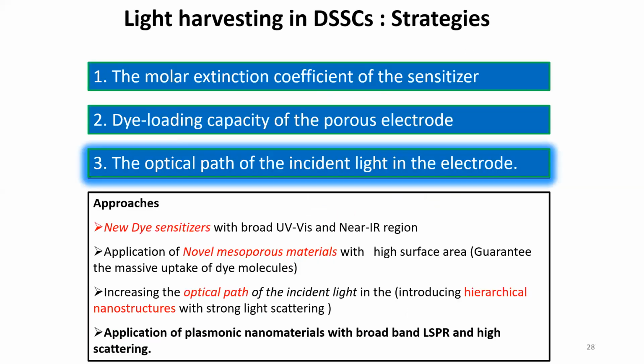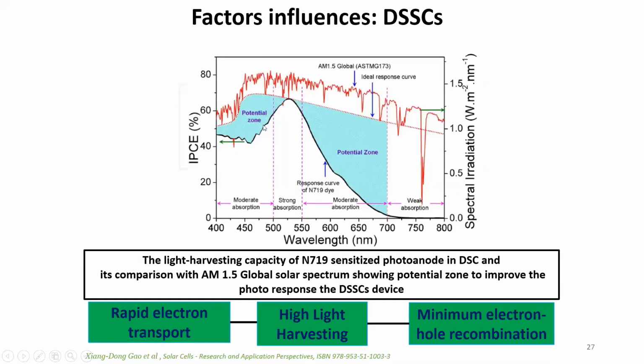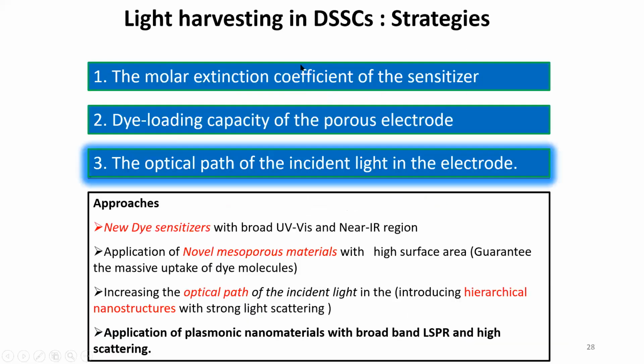So overall, how can I increase that absorption? One is that I have to use a better dye other than N719. If I use some other dye which has broad absorption, it is possible, but organic chemistry also has some limitations, that it cannot absorb light in all the regions. Up to now, the best dye available is N719. So let us take this as the base dye and work on it. Another thing is I can increase the dye loading so that more light will be absorbed, and overall I can boost the efficiency. The third thing is I can increase the optical path, with no need to increase dye loading or the dye. There is no change in the fabrication of the structure, just increase the optical path of the material to some extent.